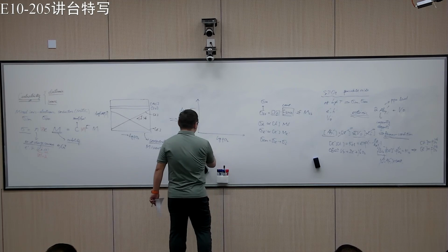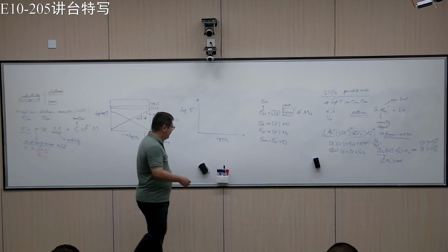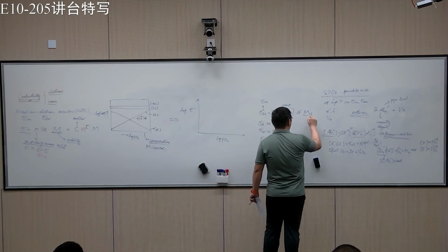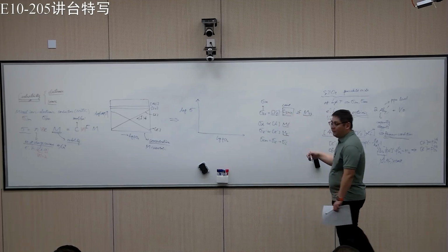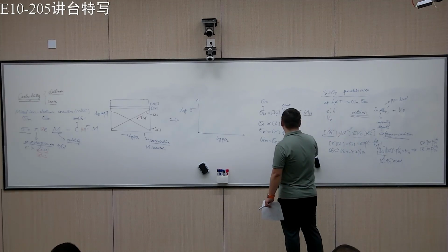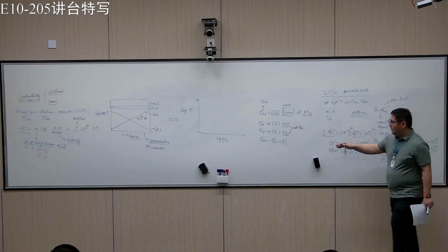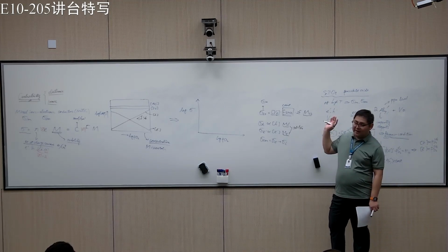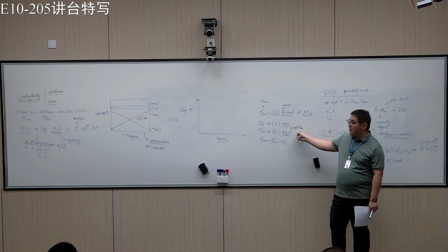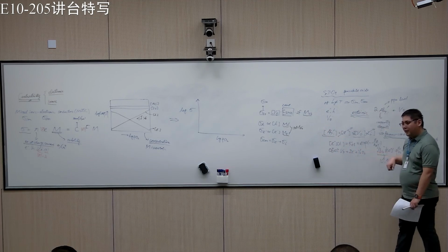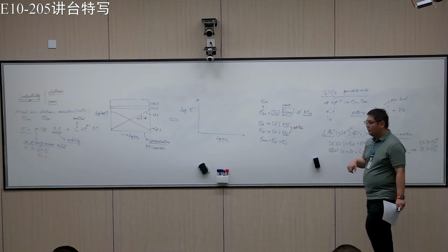All right, so let's translate this to this one. But before we do that, you need to know that this guy is much smaller than these two. Okay, so these two are much larger than the mobility of oxygen vacancies. This is understandable because the electron and the hole move much faster than ions, right? That's why at room temperature you can never have a measurable oxygen ion conductivity in strontium titanate. You have to go to something like 500, 600 degrees C, okay, to measure that.